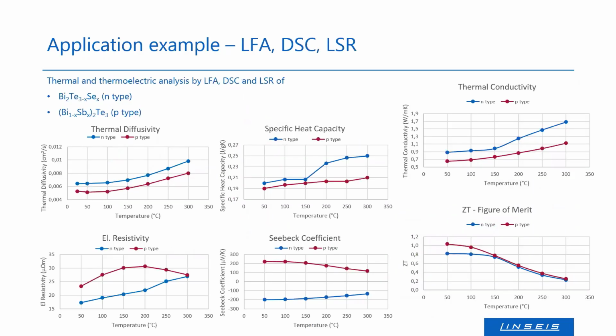And here, the last application example is shown. Here, the analysis was performed by an LFA, a DSC, and an LSR. Here are bismuth selenide samples and bismuth antimony samples, so N-type and P-type samples were characterized. The thermal diffusivity was measured with an LFA, and the same sample was used to be measured with an LSR to determine electrical resistivity and the Seebeck coefficient. With a DSC, the specific heat capacity was determined.